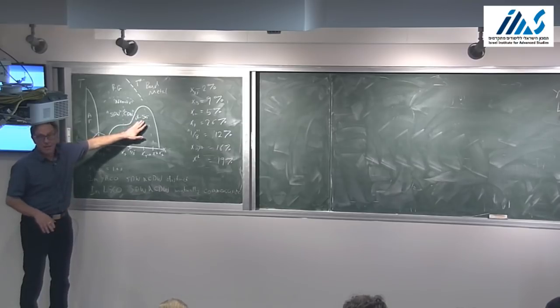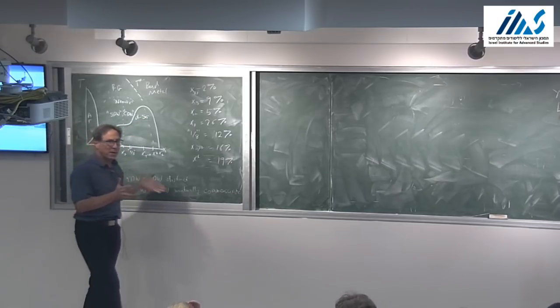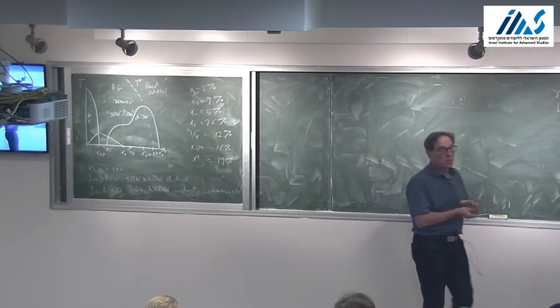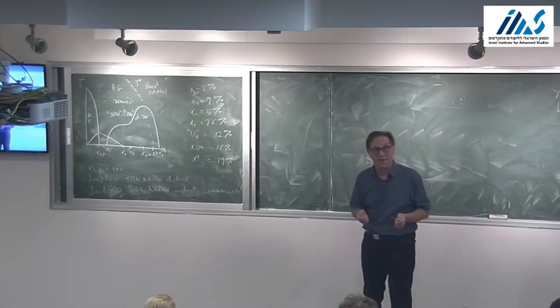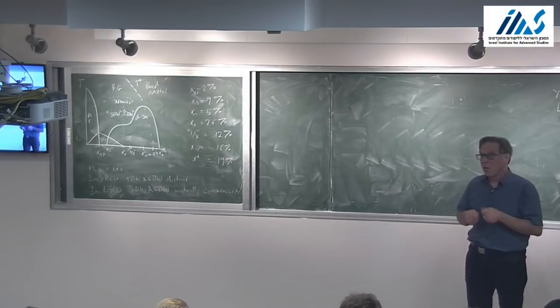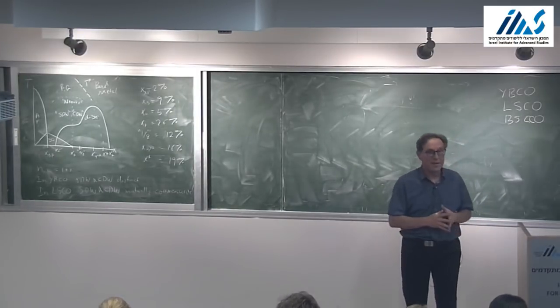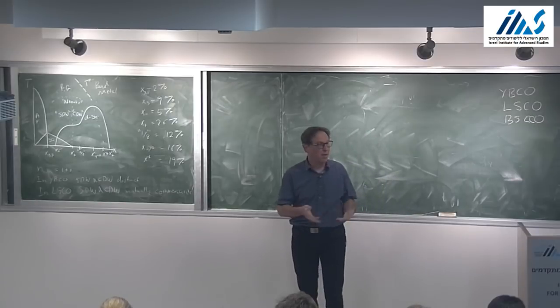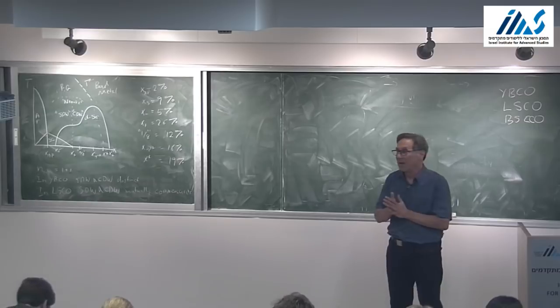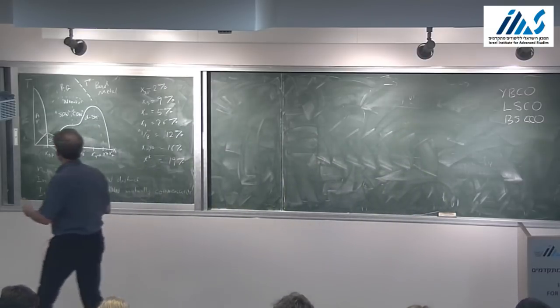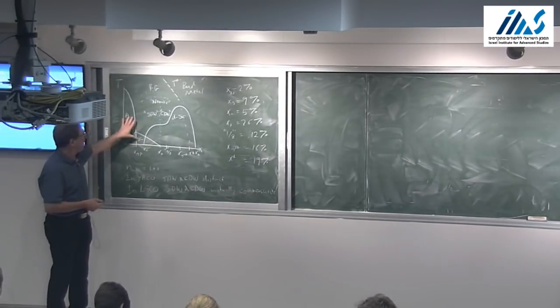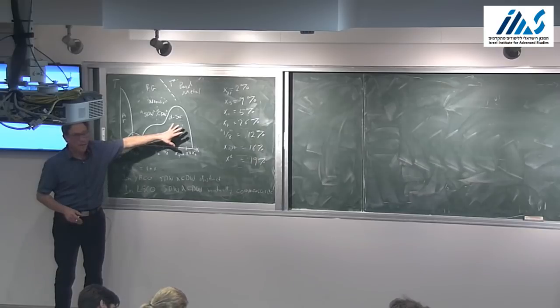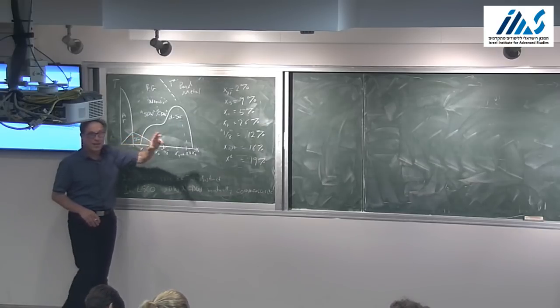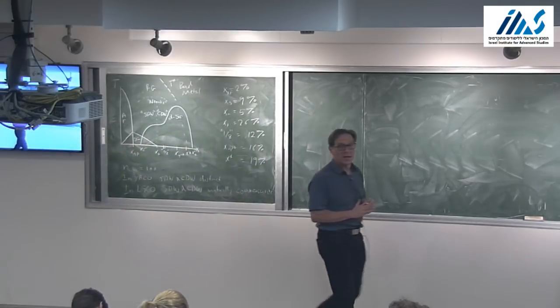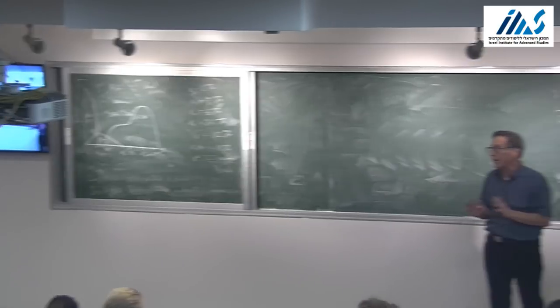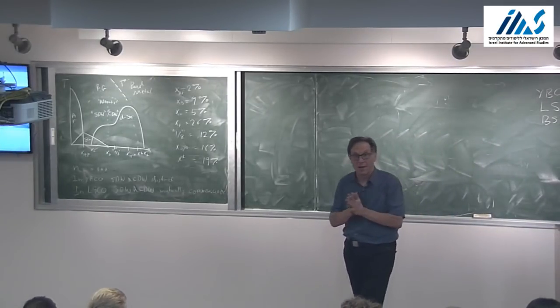But more importantly, this is a D-wave superconductor. And a D-wave superconductor, for reasons that Andre has explained, really comes from dominantly repulsive interactions. So although it's quite possible that phonons play a role in the physics, it can't be conventional, they can't be dominant. The repulsive interactions in the problem must be dominant, and of course that's confirmed as well by the prevalence of magnetism both in the phase diagram, but even when one looks far from the antiferromagnetically ordered state, if one looks locally, one sees that the local moments are still present, saying that the repulsive interactions at the microscopic level are really the dominant force in these materials.